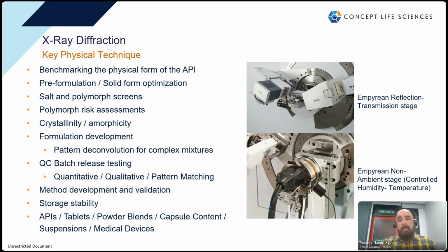Here I'm showing two different stages that we use during our measurements. On the top right-hand side, you can see the reflection transmission stage, which is the basic stage. Here you can see it in Bragg-Brentano geometry. If it moves to almost 180 degrees, it becomes a transmission stage. And on the bottom is a photo of the non-ambient stage, where you can control the humidity and the temperature of the system while you're running your X-ray diffraction patterns.